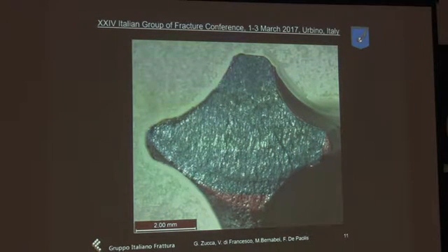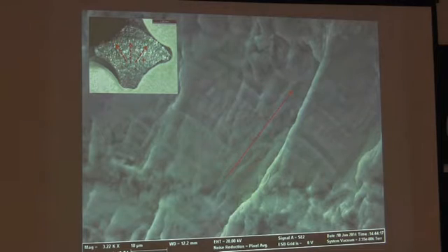except for the red part. We see a morphology that we can assume, even at low magnification, as fatigue. And in high magnification, we can see the clear beach marks of fatigue. Usually, we start to observe the fracture surface from the middle because, following the beach marks in the direction opposite to the propagation, we can find the initiation point of the fatigue.